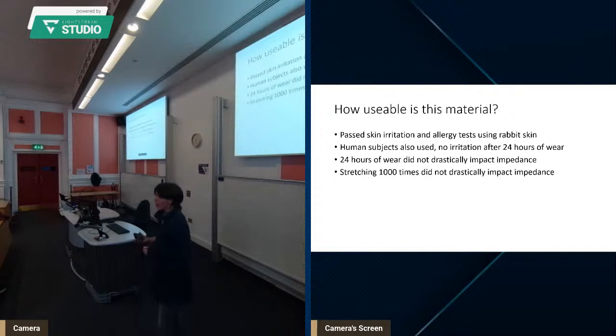I also want to talk about how using the material might affect its usability. So remember, impedance is quite an important property of this material. They found that 24 hours did not drastically make the impedance worse. It did increase the impedance a little bit, and increased impedance is worse, but it was a very negligible amount.